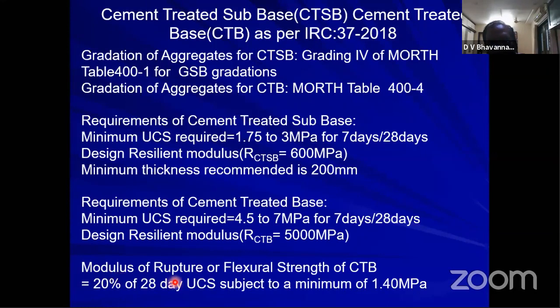Also, the modulus of rupture or flexural strength is 20% of the 28-day UCS, that is, 1.4 MPa. We have to consider these things in the design of CTSB or cement treated base. Actually, we have done CTSB in Amaravati Development Corporation, and by doing CTSB, we got a reduction in the thickness of wet mix macadam and DBM also.